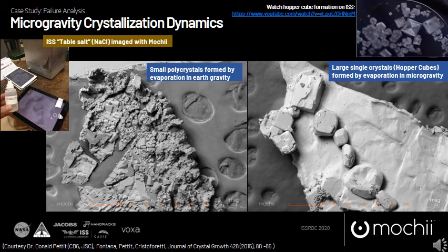ISS table salt evaporated in Earth gravity, on the left, produces small merged, sharply faceted polycrystals, just micrometers in size. The same solution in microgravity, on the right, produced massive rounded crystals called Hopper cubes that range from hundreds of micrometers to several millimeters. Crystals typically nucleate from small energy perturbations around impurities, growing into crystals from those centers.